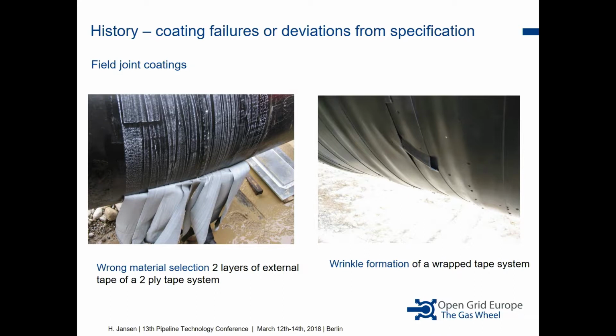If you look at the left photo, there is a typical example of wrong material selection. The specification says to use 2 tapes. The first tape, the inner tape, is a PE tape backed on both sides with butyl rubber, and this first tape is wrapped in two layers circumferentially around the field joint area. The second tape is a PE layer with butyl rubber on one side, and this is also wrapped 2 layers, minimum 50% overlap. Only this field coating compound makes a fully self-amalgamating coating system which meets the specifications.